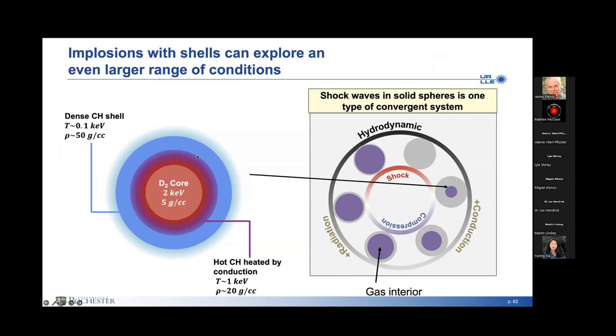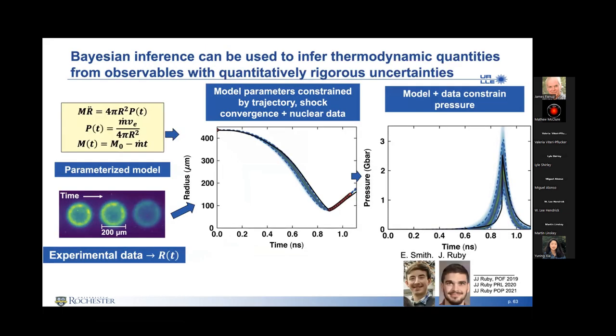Turns out you can go to higher pressure if you go to shells, and that's just because a ball can only compress so far, but a shell can squish to much higher densities. And that has been used for quite some time. In fact, J.J. Ruby and Smith have been working on understanding how to use mechanical models, essentially just following the trajectory of the shell as a function of time and using emission to get pressure as well as mass density.